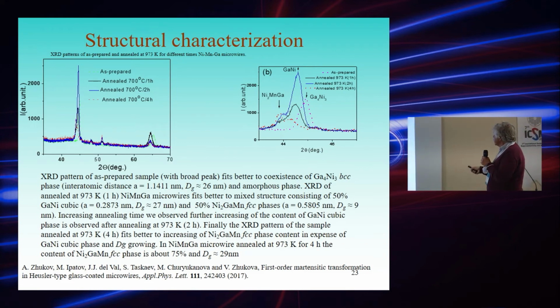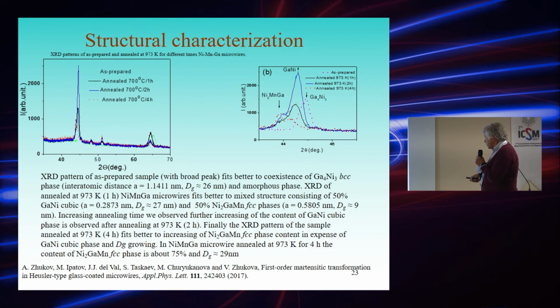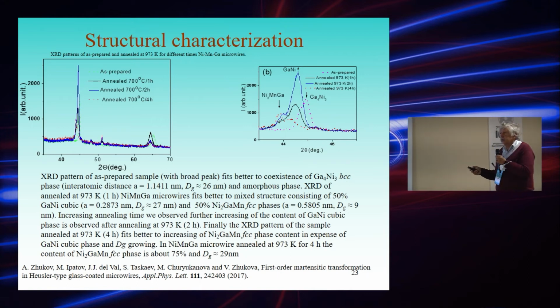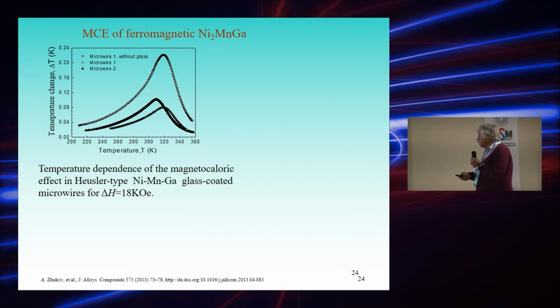As you can see in this picture, the as-prepared sample presents quite a broad X-ray peak, which could be attributed to the coexistence of a BCC phase and an amorphous phase. Then after annealing, you can see a clear change of the structure. Finally, after annealing at conditions where we have hysteretic behavior, we found FCC phase, about 75%, but still all the materials present nanometric grains. So these materials present crystalline structure, even after annealing.